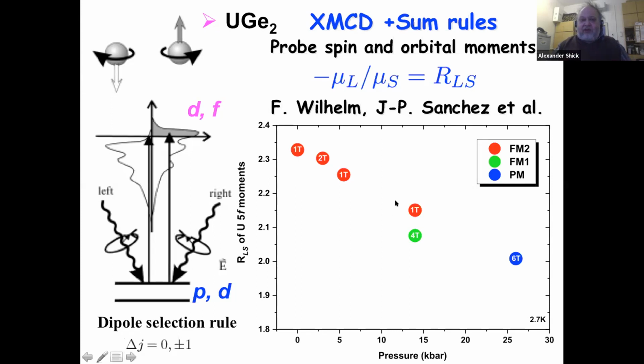And you can measure not only the spin and orbital moments, not only the spin moment, but also the ratio of the orbital to the spin moment using the sum rules. And that's actually what was done at ESRF by Fabrice and collaborators. And here is the result. This is the RLS ratio versus pressure. And you see that not only the total magnetization changes when you go from FM2 to FM1, but also the ratio is changing. It is getting smaller.